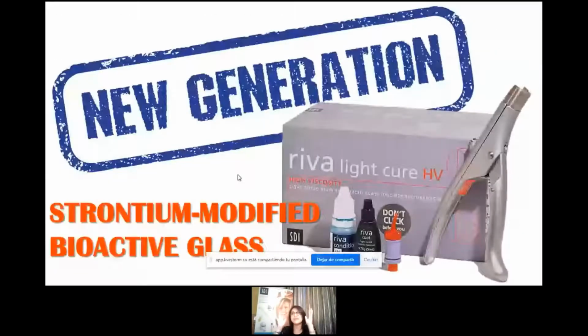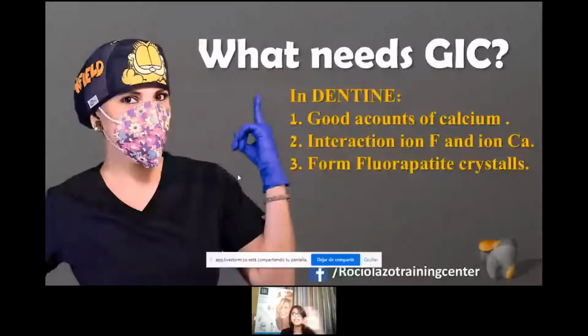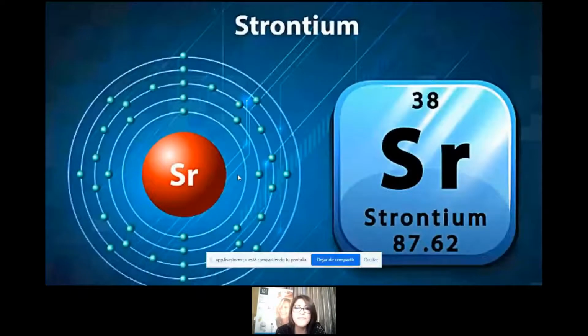So thinking of a restoration with the properties of bioactive glass, we have this new generation of glass ionomers. This new generation of glass ionomers are the strontium-modified bioactive glass. With this kind of materials, you can restore your cavity definitively. Okay, remember what glass ionomers need to be successful in dentin? Do you remember? First, we need good amounts of calcium, interaction of fluoride ion and calcium ion, and form fluorapatite crystals. Okay, the problem is that in defective dentin, we don't have good amounts of calcium. That's our problem, okay? But right now, with this new generation of bioactive glass ionomers with strontium, we are not going to have this problem.